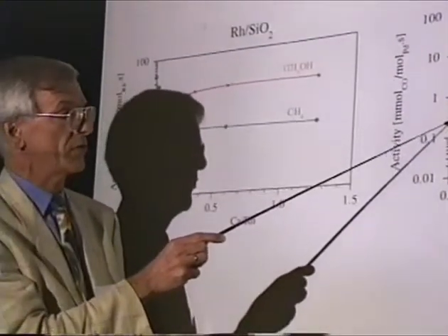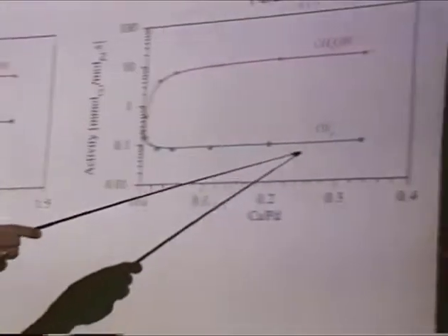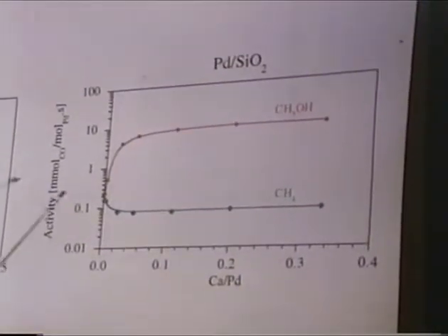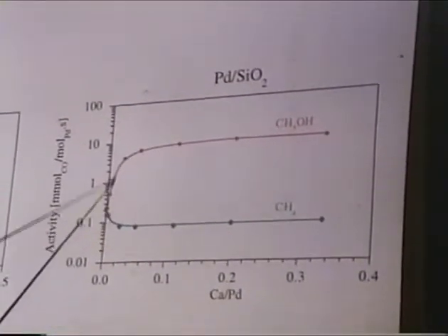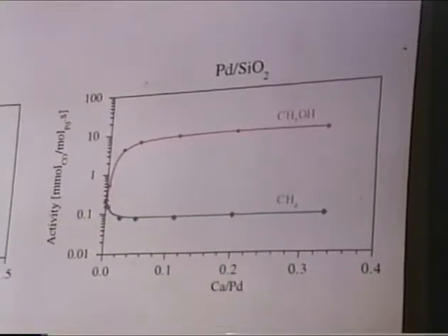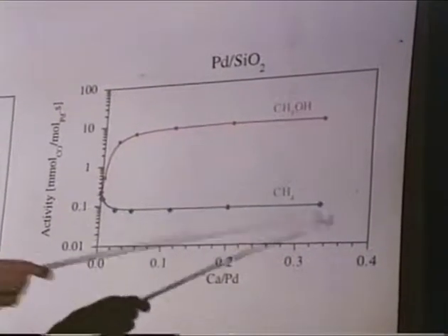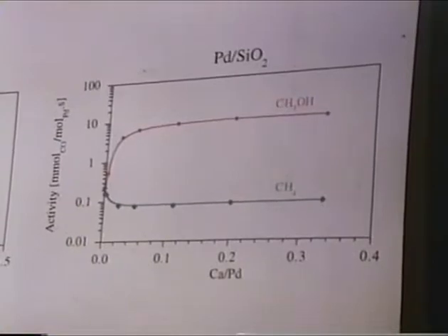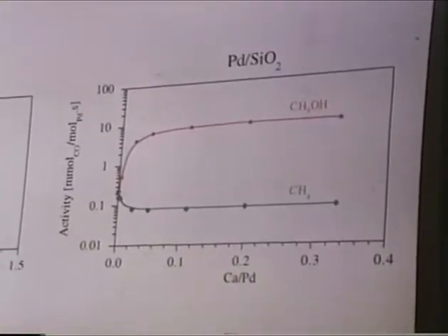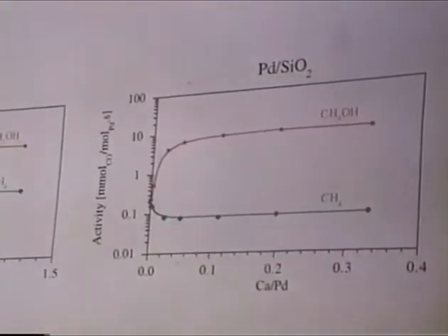Here is a slide with this as a function of the calcium loading, and also you see it for the rhodium. Let's look at the calcium first. The methane was low in the first place, so you suppress it, and then you are at a constant, very low level of methane, and the methanol goes up, and there it's constant. And this means that you can, on this catalyst, run and make methanol at 99+% selectivity.